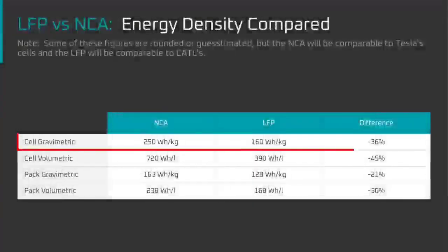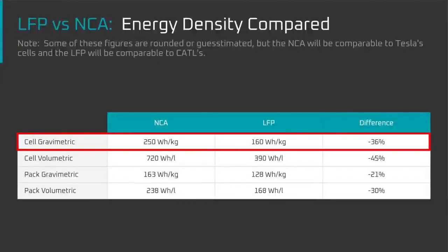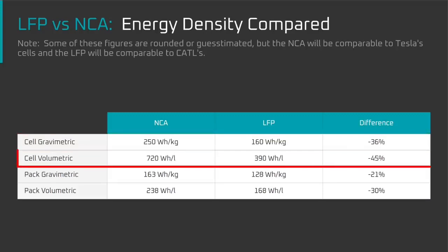Currently, NCA battery cells like Tesla's are above 250 watt-hours per kilogram, and LFP battery cells like CATL's are above 160 watt-hours per kilogram, or 36% less. As for volumetric energy density, NCA battery cells like Tesla's are around 720 watt-hours per liter, and LFP battery cells like CATL's are around 390 watt-hours per liter, or 45% less.